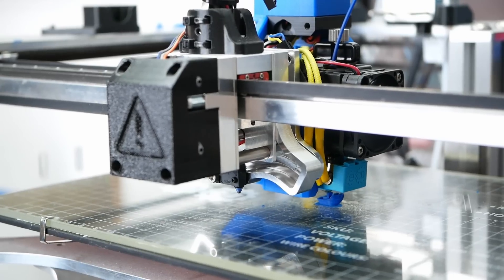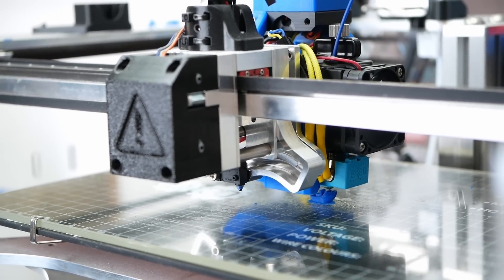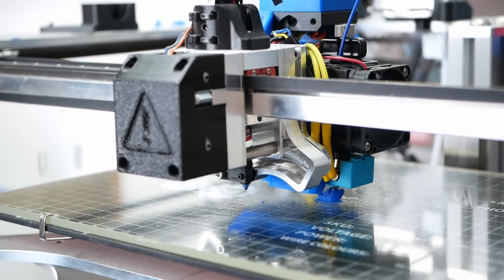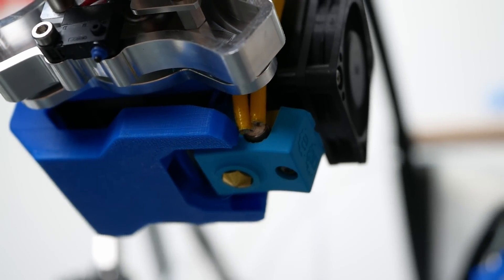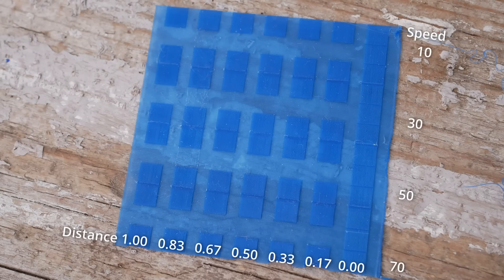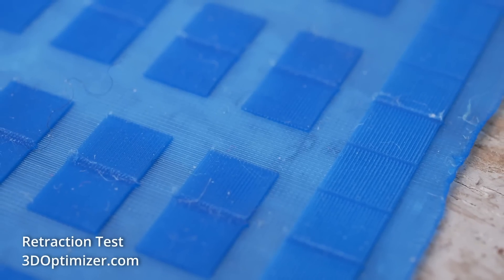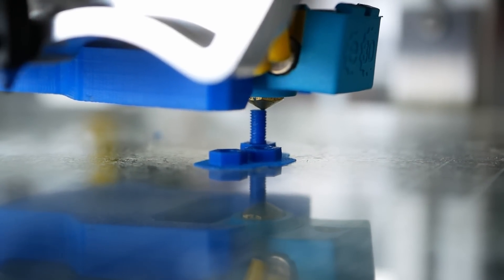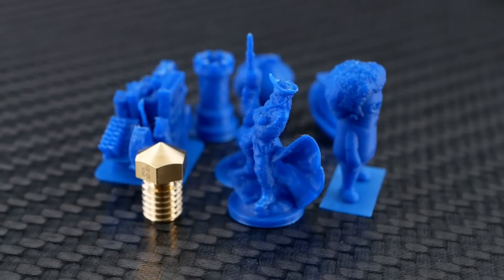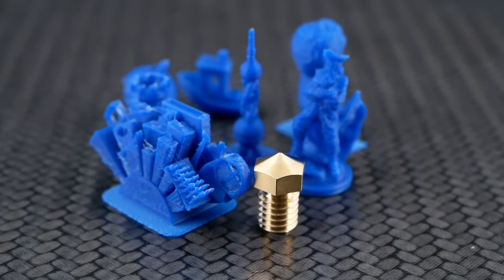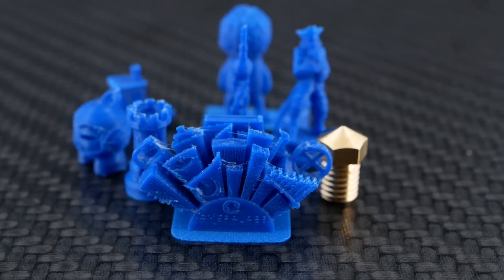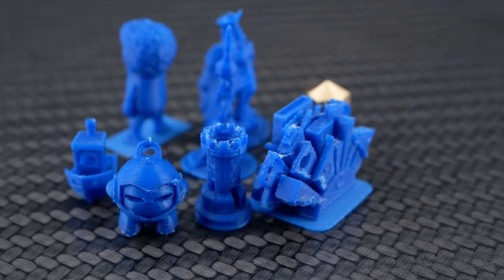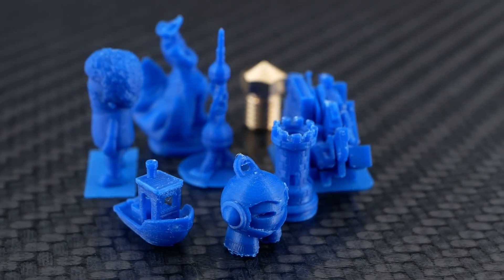Part cooling was even more important because due to the tiny parts, the nozzle and heater block is always close to the part and heats up the print. Switching the part cooling and adding a silicone sock helped quite a bit. Due to the tiny nozzle, I was able to reduce retractions to a minimum on the Hemera and 0.5mm was way more than enough to prevent stringing. Using this profile I was able to print a ton of well-looking parts at that scale. I scaled most of them down to 25% since many were designed to be printable with a 0.4mm nozzle.